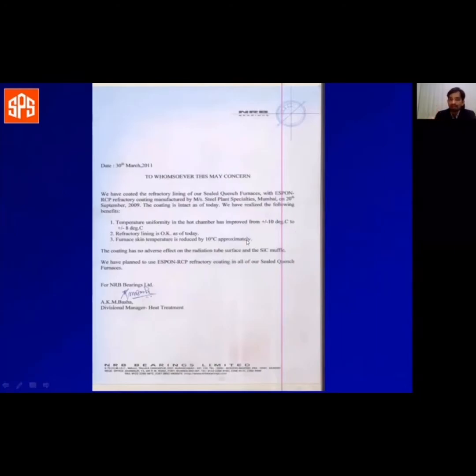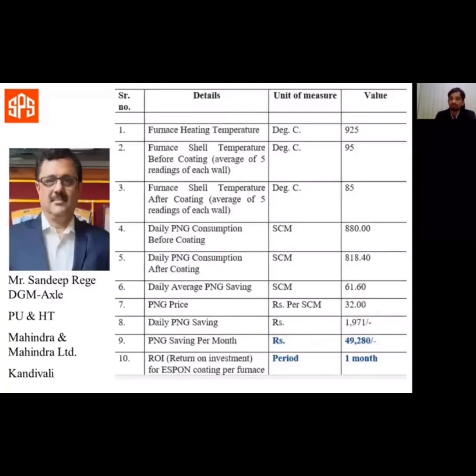So with a reduction of 10 degrees in furnace outer shell temperature, what savings can you expect? Well, the answer is given by Mr. Sandeep Rege, DGM-Axle, PU & HT, and his heat treatment team at Mahindra and Mahindra Limited, Kandivali, Mumbai. They meticulously verified the fuel consumption in their furnaces before and after using the refractory coating. A fuel saving of 7% was achieved in this case. With a fuel saving of 7%, the return on investment of the refractory coating works out to less than 1 month.